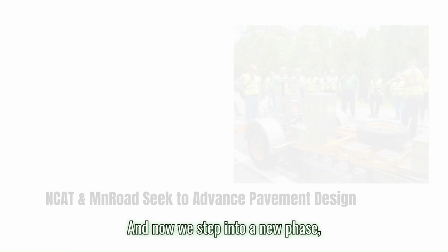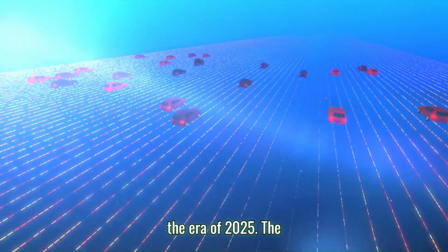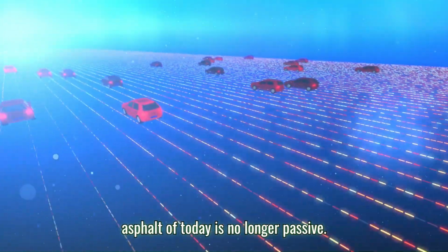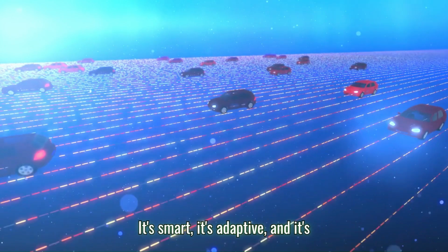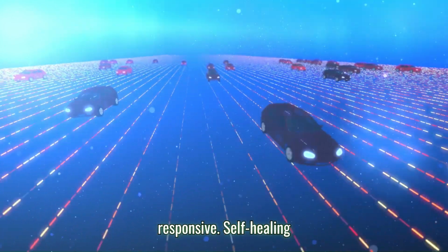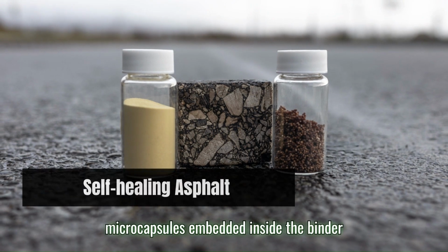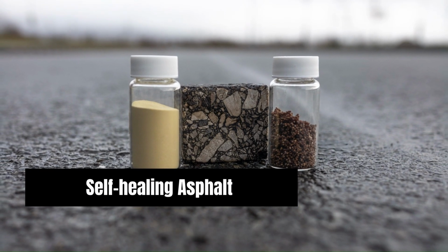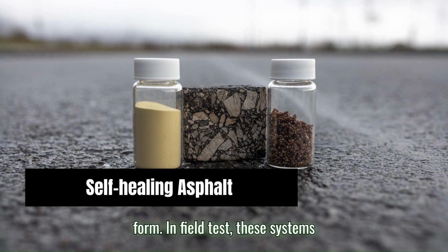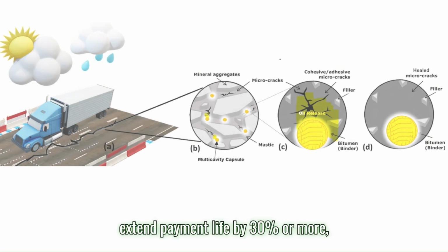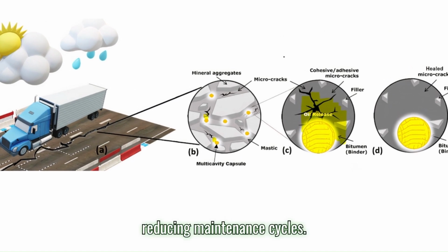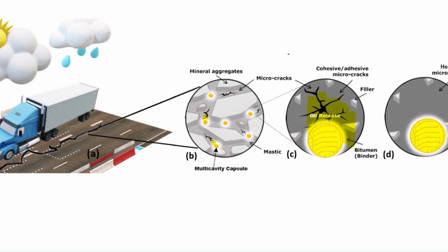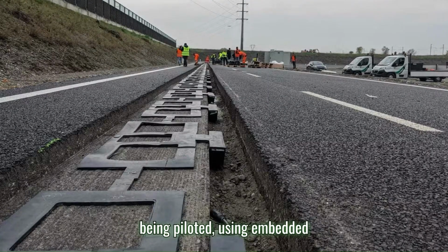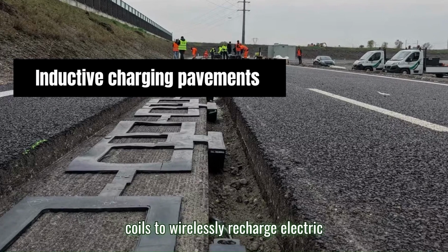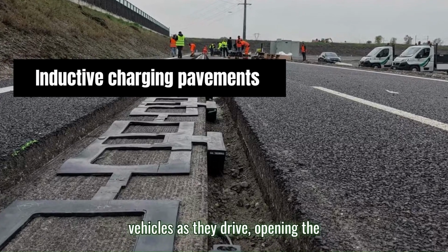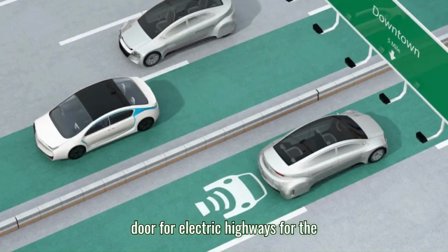And now we step into a new phase, the era of 2025. The asphalt of today is no longer passive. It's smart, it's adaptive, and it's responsive. Self-healing asphalt is being trialed, with microcapsules embedded inside the binder that release healing agents when cracks form. In field tests, these systems extend pavement life by 30% or more, reducing maintenance cycles. Inductive charging pavements are also being piloted, using embedded coils to wirelessly recharge electric vehicles as they drive, opening the door for electric highways of the future.